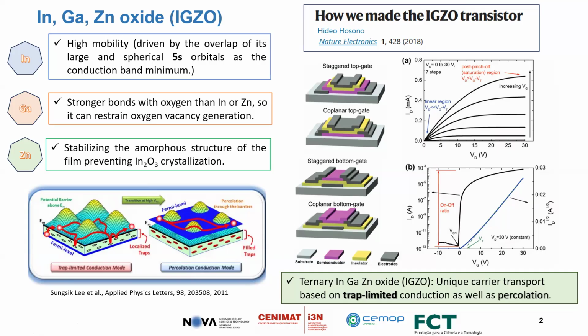Look, for example, at the gallium here. It makes stronger bonds with oxygen than indium or zinc, so it can restrict the oxygen vacancy generation, which on a thin film transistor should be restricted. So we need a certain property of the channel material of the transistor. However, if we use the same material for another electrical device, like a resistive switching device based on IGZO, then it should be engineered differently. The presence of zinc, these elements I am explaining, is inside just the thin film transistor, not inside the resistive switching device. The zinc stabilizes the amorphous structure and prevents indium oxide crystallization.